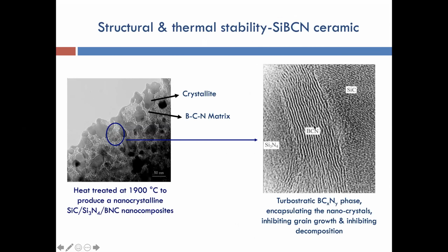So this is what I call a very good microstructural design in order to make a material stable by around 500 degrees Celsius more, which we could not have seen in silicon carbonitride. And how do we achieve that? We achieve that by simply having these boron, carbon, nitrogen turbostatic layers, which sandwich several nitrides and carbides, and encapsulate the silicon nitride in such a way that the silicon nitride doesn't get decomposed. So this actually goes against thermodynamics.